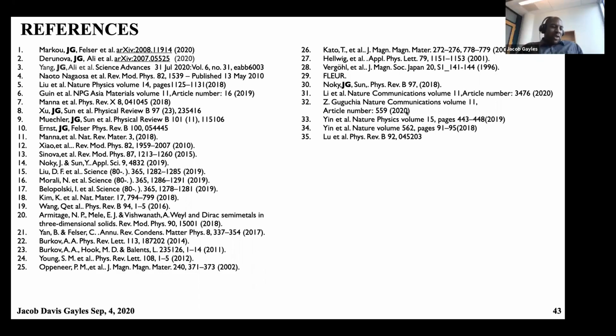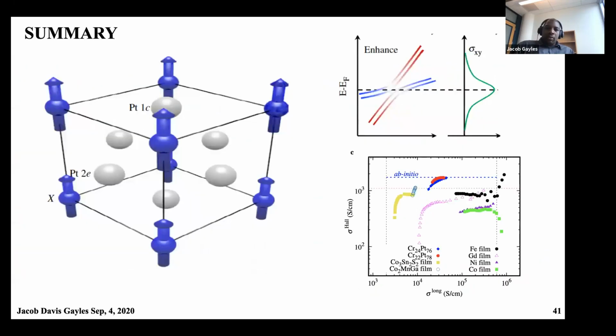So I would say they're mid anisotropy. They have hard magnetic properties, but they're not completely hard magnetic. One of the reasons it's on arXiv is that we wanted to get the work out there quickly, but we're still having trouble getting the transition temperature correct, which we believe to be around 600 or 700. It's actually quite complicated to measure the difference between these two magnetic moments.